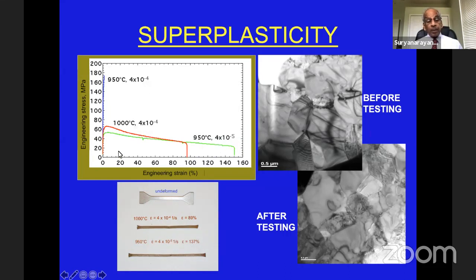of minus 5, then you can observe elongation almost up to 150%. Even at 1000 degrees at higher strain rate, you can see almost like 100% elongation. This should be compared with what we normally see in a coarse grain material.